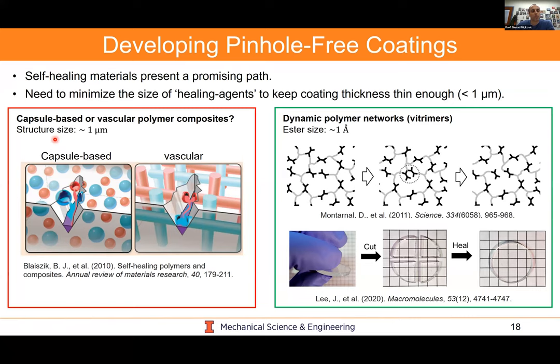This can actually be done with capsules or it can be vascular based. And there's been lots of fantastic work on this approach published in great journals like Nature and Science. Part of the problem with this approach is the fact that these capsules have a limitation on how small they could be. Given that we want the coating to be fairly thin, on the order of a micron or less, it turns out creating these capsules is actually very hard to do for that particular thin coating application. So we're a little bit limited on what we could do with this sort of self-healing approach.